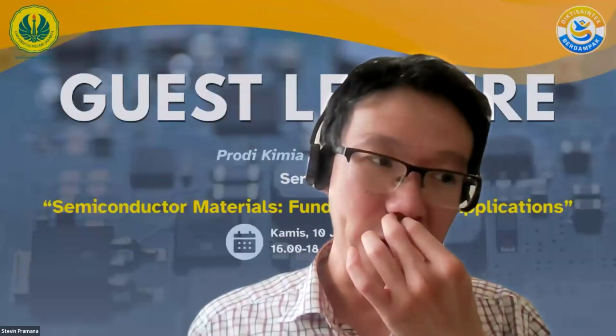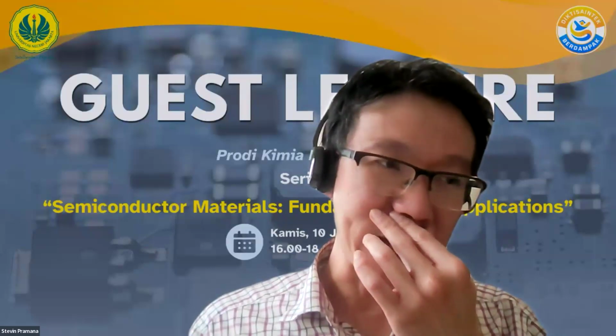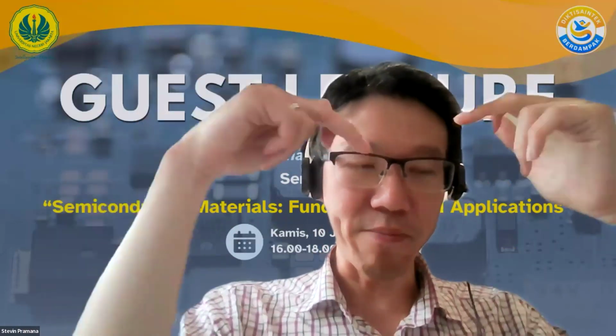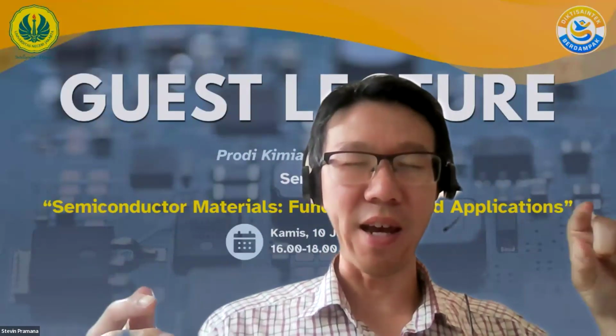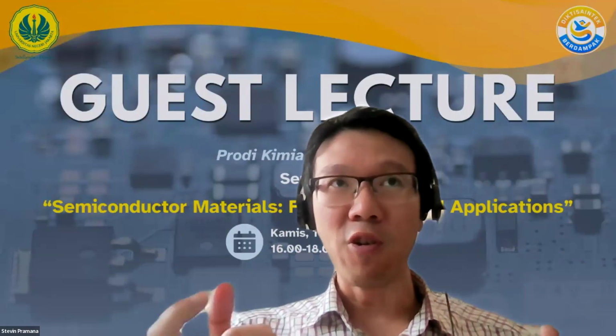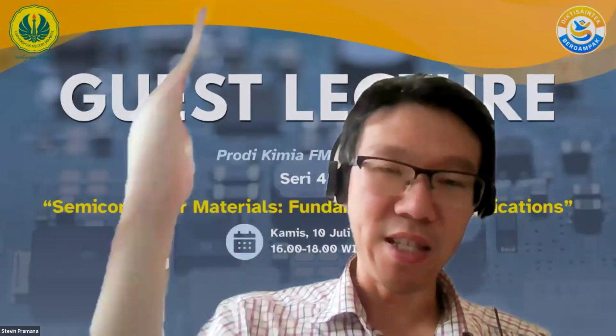Yeah, it is possible. Usually for XRD, if we want to analyze a thin film, we can't really use the bulk configuration, because the bulk configuration uses Bragg-Brentano, meaning the theta is coupled. What people normally do is use grazing incidence X-ray diffraction. Usually we set the incident angle to probably 1 or 2 degrees, because at 1 to 2 degrees the interaction volume is already probably like 100 nanometers or so. Then the diffractometer just scans theta from the detector side.